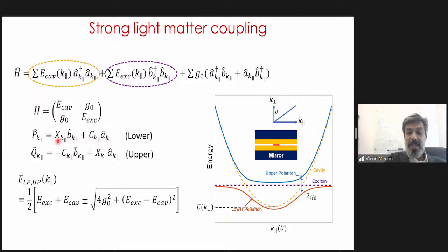So all that will happen is this XK and CK change in magnitude as I traverse the in-plane momentum of the structure. And this is the k parallel of the cavity. So this is my cavity structure, two mirrors, my material inside, and I'm looking at it as a function of in-plane momentum. And as I go from here to here, I change the constituents of this quasi-particle, making it go from something that is very photon-like to something that is very exciton-like or matter-like. And then the two eigenstates are given by this, with the plus and minus corresponding to the energies of the upper and lower polaritons.